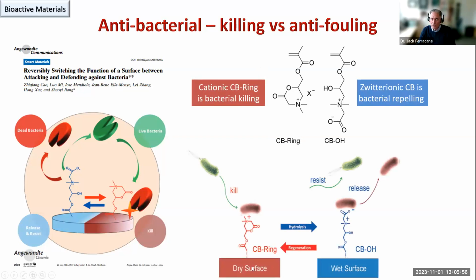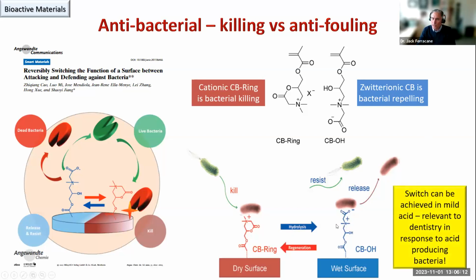So here's an example of on a dry surface, the material is bacterial killing because the ring is closed. When the surface becomes hydrated, the ring opens up and basically it ejects or removes or keeps the bacteria from sticking to the surface. And the interesting thing is this switch can take place in a mild acid solution, which is interesting to us because that's what we experience as caries might be forming and bacteria are producing acids. We get a mild acid where we can actually get a Zwitterion to switch and actually repel the bacteria.